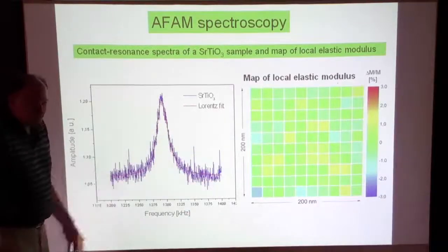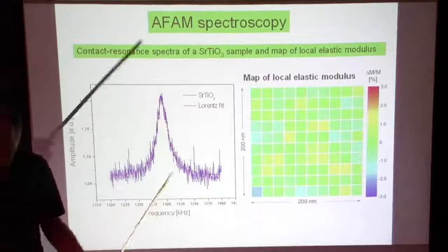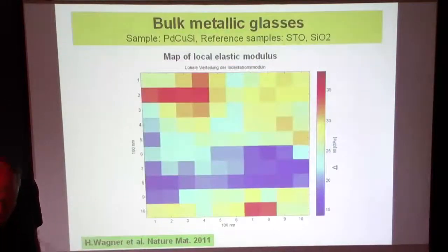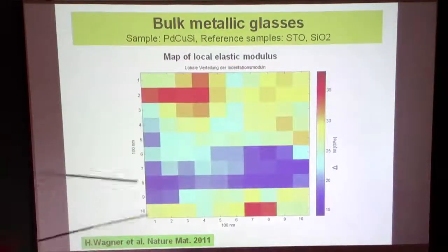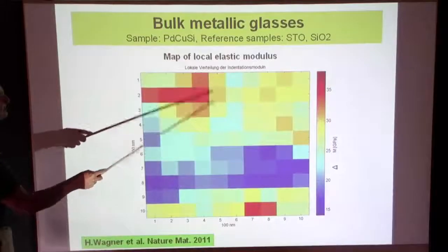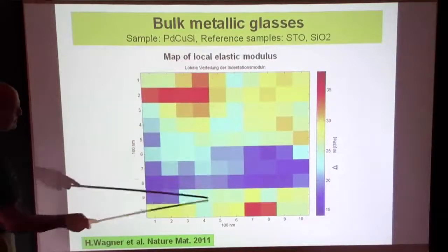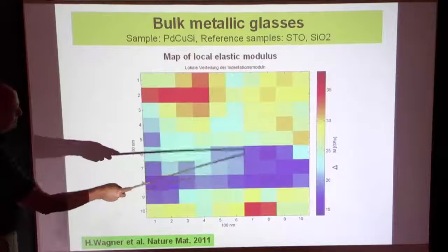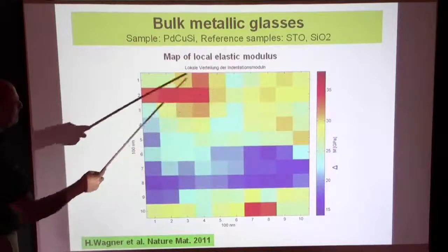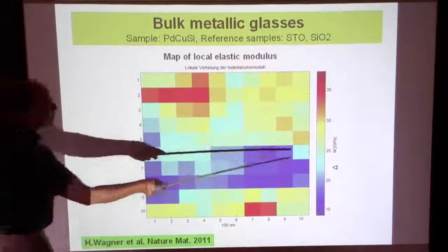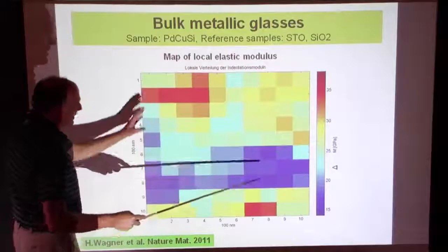It's a crystal, it's a single crystal. The same is actually true for quartz. If we now go to bulk metallic glass, you see there is a huge variation. Actually, this is again this palladium copper silicon, and certain bands actually show up here already, certain areas which have a high modulus, low modulus variation of that.